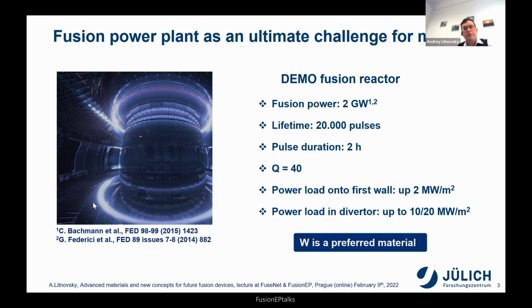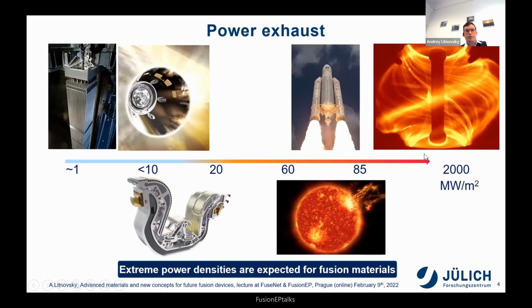So it was decided to select tungsten as the baseline material, which has a number of very good features, a number of advantages like high melting point, relatively low activation, low sputtering by plasma particles, relatively benign tritium retention. And this material was selected as the baseline material. To understand, however, what this megawatt per square meter power density means, we can go to the next slide, which shows, in live examples, what it means.